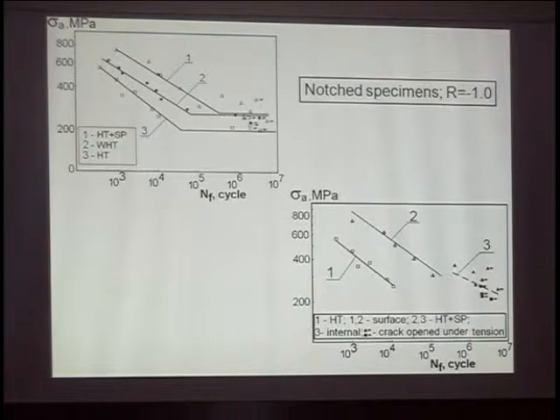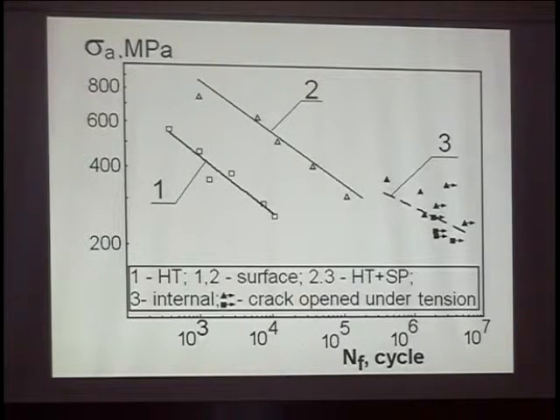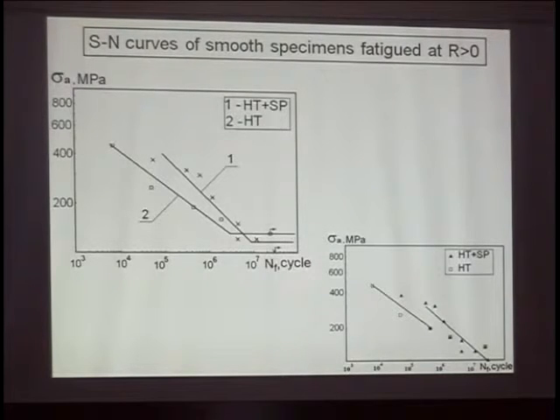That's why, based on this thinking, we reorganized all the fatigue curves that have been announced on the previous slides. For instance, this curve, this area, is not an area for material cracking at the surface. This area is for cracking subsurface. So it should be clear to realize that there are not one or two curves, for instance, for this database. There is a curve which reflects material cracking at the surface, and another one which reflects material cracking subsurface. The same results can be seen at high magnification and for other parameters, as in the curve for HT plus SP, high temperature tempered material, and surface hardened.